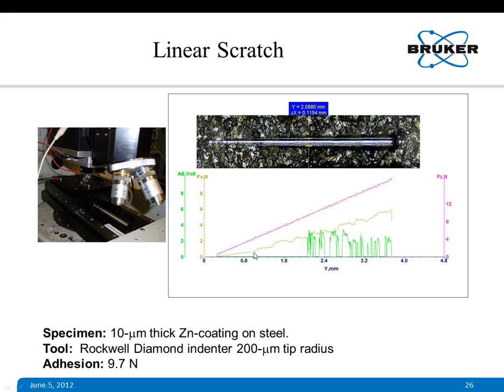There is some kind of instability which started somewhere here at very small load, probably about 5 Newton, but the complete failure of the coating occurs at about 10 Newton, somewhere here, which is confirmed by acoustic emission measurements. So acoustic emission, resistance, and lateral force measurements are different parameters which will definitively indicate the point of failure of the coating, from where we can calculate the scratch adhesion of a coating that can be compared with different coatings.